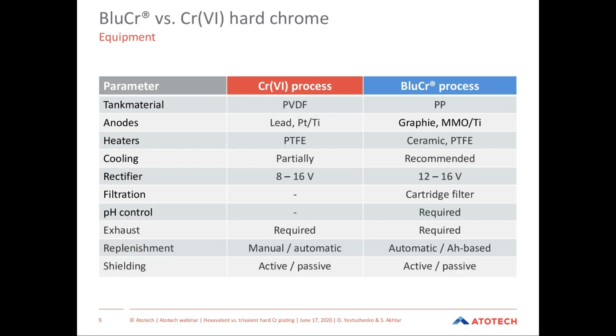As the BluCr process is less corrosive compared to the Chrome 6 bath, it is compatible with the cheaper plastic liners like polypropylene. So polypropylene can be used as a tank lining material. No hazardous substances are used within the anode materials, so you can operate BluCr without lead anodes. Rectifier requirements are comparable. Filtration of the bath is recommended. And pH control is essential for the BluCr process.